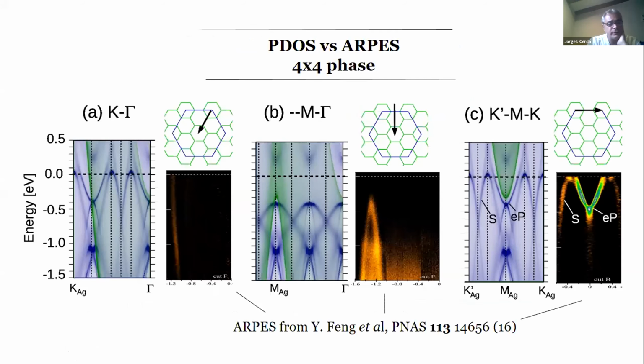When we want to interpret what is known about the ARPES data for this phase, we compare against the work of Feng et al., as I showed here. They measured ARPES along three different directions. Here are the experimental ARPES data, and here is what I've decided to place. We just show the silicon band structure of the reconstruction of the 4x4 phase in blue, and on top of it, I've superimposed the signal from the silver (111) surface, folded.